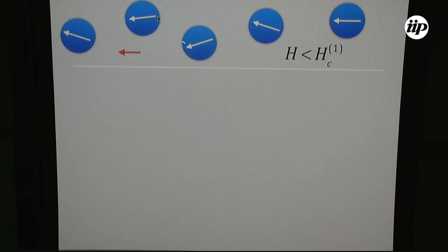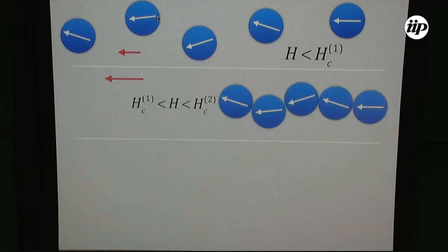Well, if you imagine, for example, these magnetic particles randomly distributed in the magnetic colloid, if you apply a magnetic field smaller than the first critical magnetic field, what you have is basically the orientation of the moments, but without the formation of macrostructure. If you increase the field further, between this first critical field and the second critical field, you have the formation of some lines. Okay, they align, and more than this, they attach one to the other and make this type of linear aggregation. We will basically study this type of structure in the following.